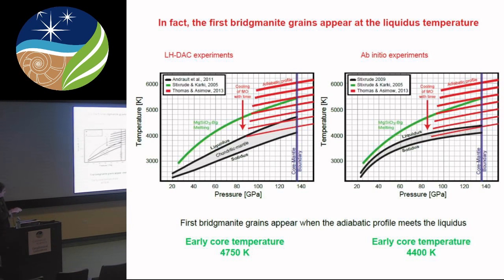What I can say here is I think there are two models remaining alive. One other model has been withdrawn. One is the possibility that the curves of the liquidus are relatively flat, based on our measurements that I will show you in a minute. And it could be more curved like this. It's ab initio experiments from Stixrude 2009. And the temperature of the liquidus here or there is not that high. It means that when you have a magma ocean and you cool it down and start crystallizing the mantle, the temperatures are actually relatively low, like 4,700, 4,750 K, or even lower here, 4,400.